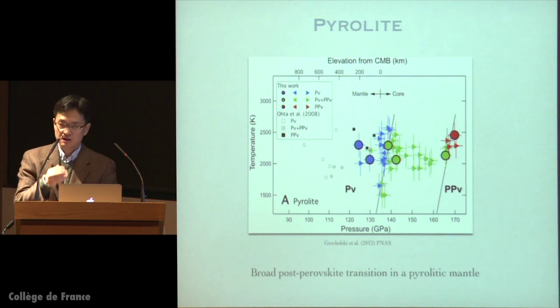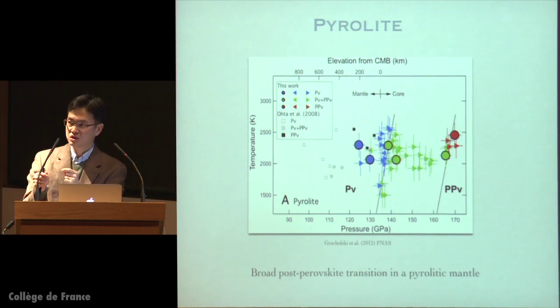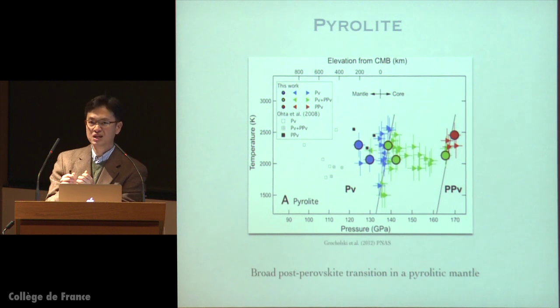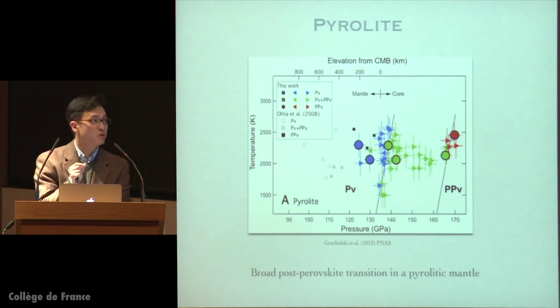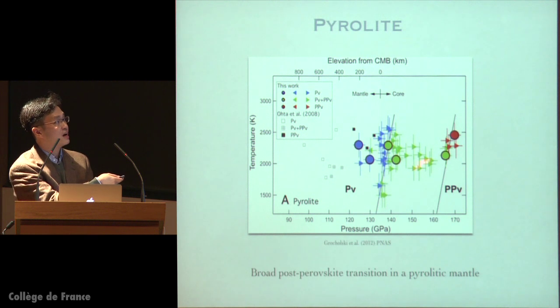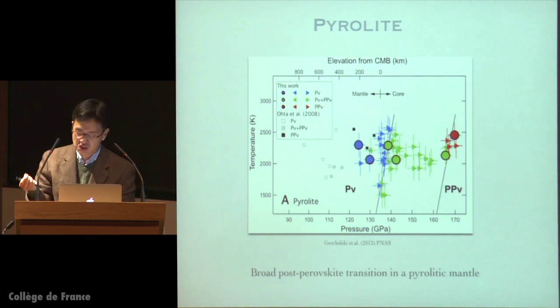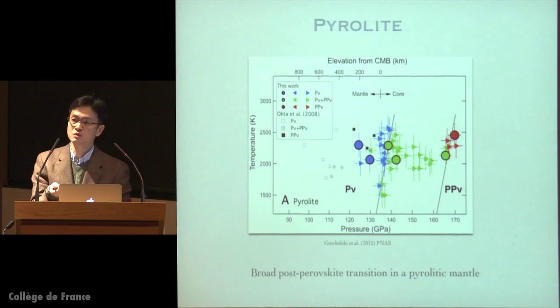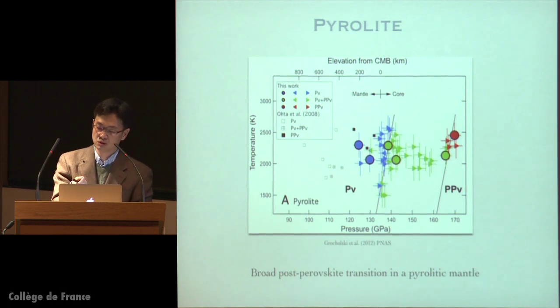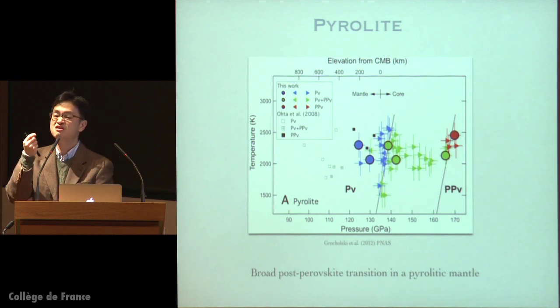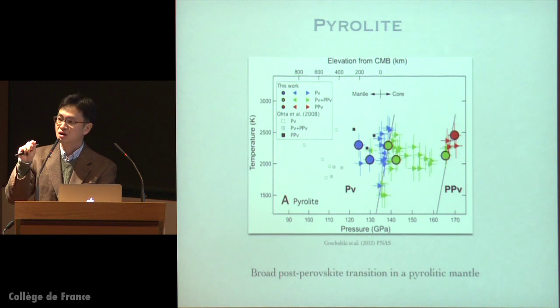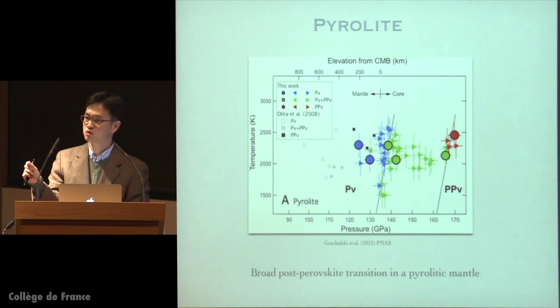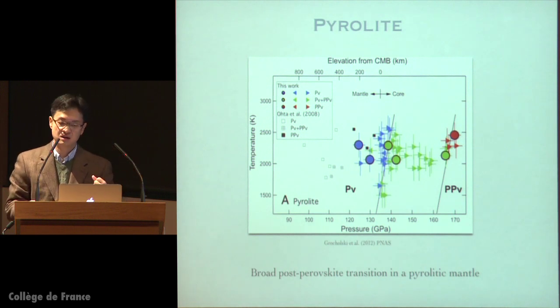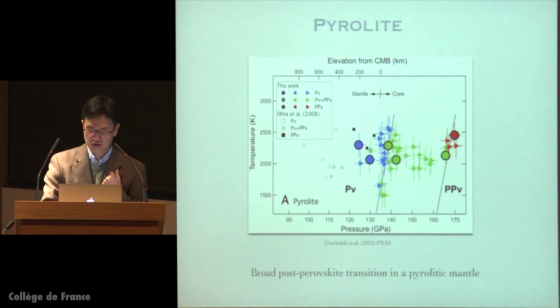And now, like I showed you before, pyrolitic composition also generates ferropericlase. So you would expect that pyrolite would also have smaller thickness. But in fact, we find it's not the case, as shown by this data. In fact, we have about 400 to 600 kilometers of thickness. The reason is that there is aluminum that makes the difference. In San Carlos olivine, we don't have aluminum. In pyrolite, we have aluminum. And aluminum has a thickening effect and deepening effect. And there is no other phase that can contain aluminum in pyrolite other than perovskite and post-perovskite. So there's no secondary phase that can play the game for the sharpening of the phase boundary.